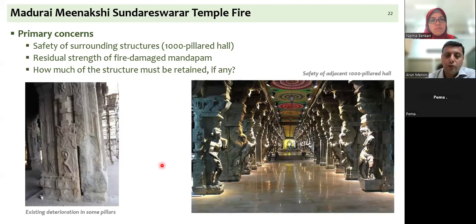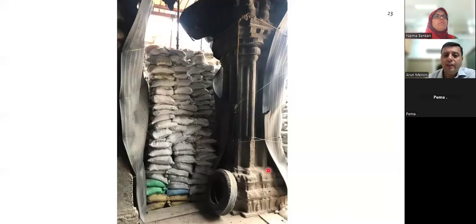That was the situation. So the first thing that was done was, of course, to ensure that eventual collapse of the structure does not affect the neighboring construction, which would be a big loss. And therefore, padding with sand, padding with soft material that will ensure that any untoward collapse does not cause debris and heavy material to fall onto the other sculptural structure, the other mandapam. That was an important step that was taken.